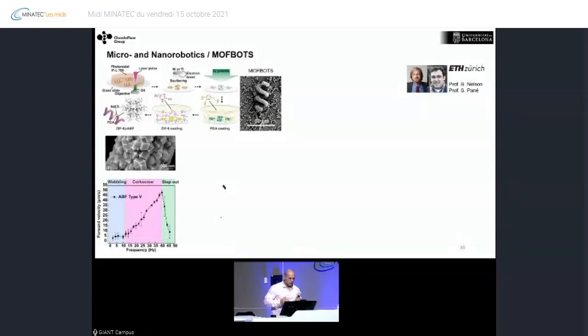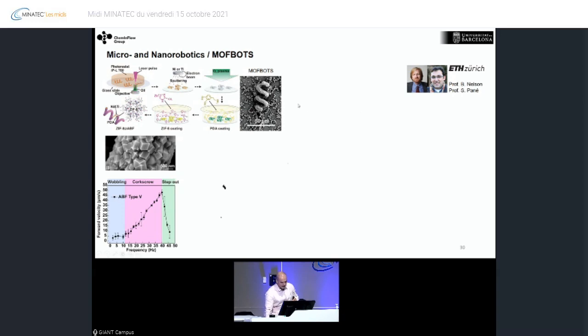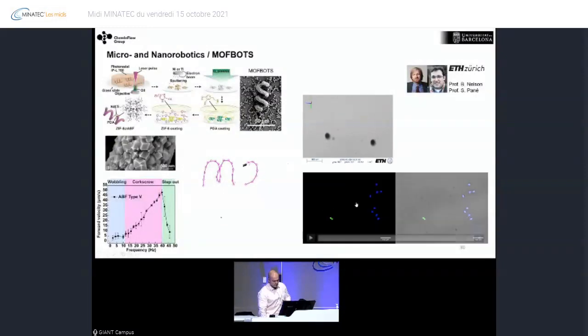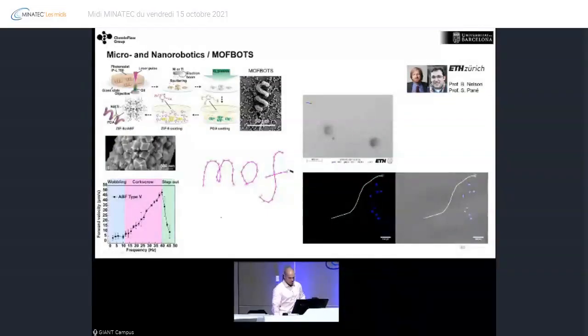motion, direct motion. So the idea here was to combine this MOF chemistry with micro and nano robotics. What we did is to grow these MOF crystals on top of the micro nano robots that Professor Salvador Pané is developing in his group. And then we can control the motion of these robots. You can see here, we can position them in different directions, so we can move them in 3D. One thing we did, as you will see in this video, is that the MOFs here are embedding rhodamine B, so we can direct them in a cell culture and position them in the cell where we want to do the drug delivery, okay?